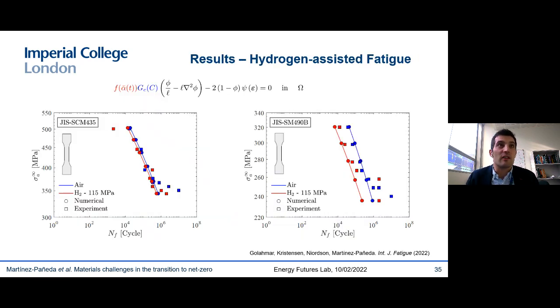And finally, we have extended the framework to fatigue. We just need to add a fatigue degradation function, and we can then deliver predictions based on the material toughness, nominal material properties, and the loading history. For example, here you can see how we can produce what are called virtual SN curves with and without hydrogen, and we see a very good agreement with experiments.